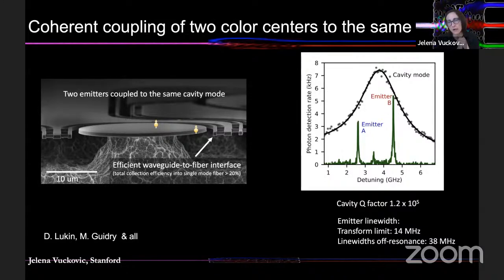And here we relied on silicon vacancy and material orientation, which leads to this dipole orientation in the vertical direction. That's why these dipoles are shown as vertically oriented. And that's also the reason why we relied on the microdisc resonators, so that we could work with the TM modes that couple well to these TM-oriented transitions. So here you see two different color centers, two different emitters that are positioned inside of the microdisc resonator and the cavity resonance. We have a really nice Q factor, and we have also very narrow emitter line width, despite this whole process that we go through of grinding and polishing and subsequent resonator fabrication. And around the resonator, we also have the waveguide that is coupled outside of the cryostat.